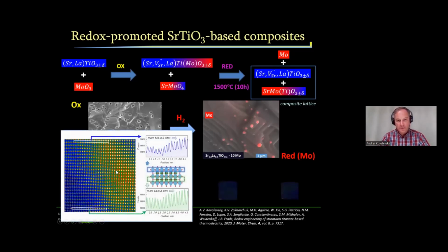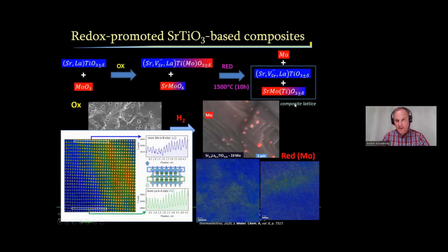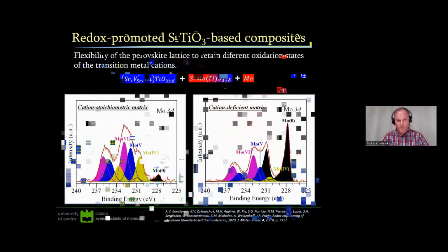We also observe the formation of islands of strontium molybdate perovskite inside the strontium titanate matrix. These islands are very tiny, very small, probably 5-10 nanometers. This could produce a very interesting effect on the thermoelectric performance.